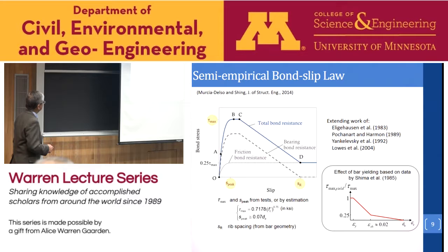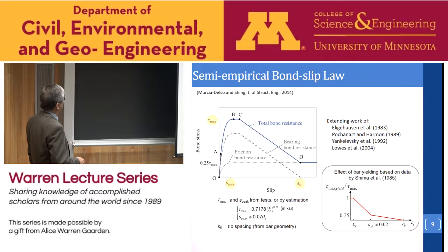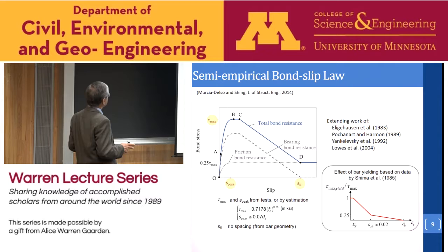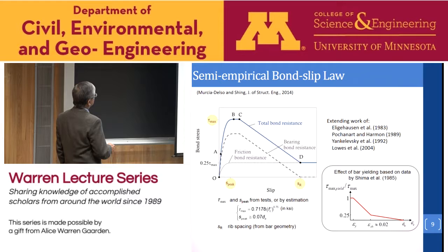Now, in this model, we divide the bond resistance into two parts. One is the bearing resistance, and one is the friction resistance. So the sum of the two gives us our total bond resistance. Okay? And the beauty of this model is that it's very simple, and it only requires three physical parameters to calibrate. One is the bond shear resistance, the maximum bond shear resistance. And the second is the slip of the bar when reaching this peak resistance. And the other is the point at which all the bearing resistance will be dropped to zero.